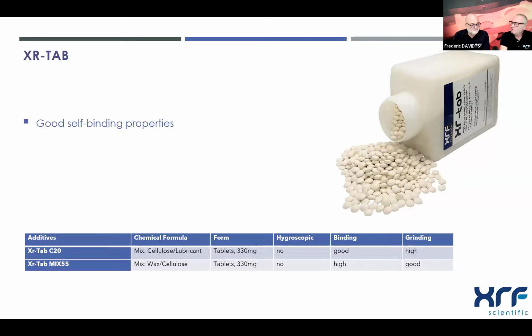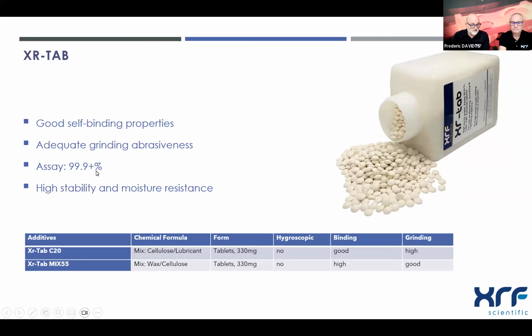Depending on the case, so less consumption and better grinding. Yeah, exactly. So at the end, we have good self-binding properties using that, adequate grinding abrasiveness, and of course the purity is good for XRF purposes. And high stability and moisture resistance, like I explained. We don't want to have water moisture in the pressed powder, and we need to leave the tablets close to the grinder or to the press, so we don't want these tablets catching water. So it's very important.